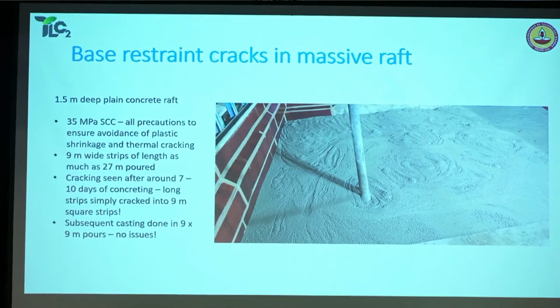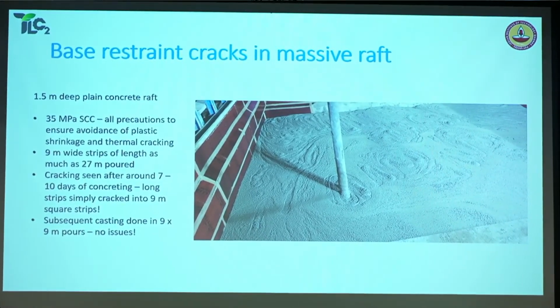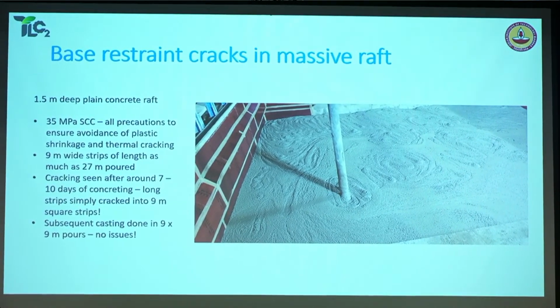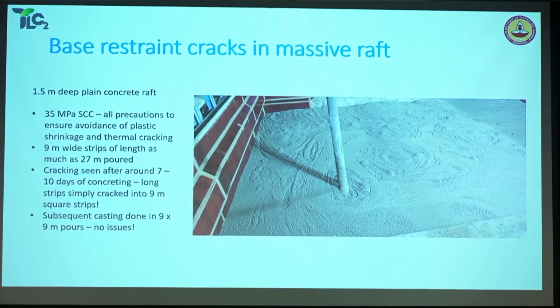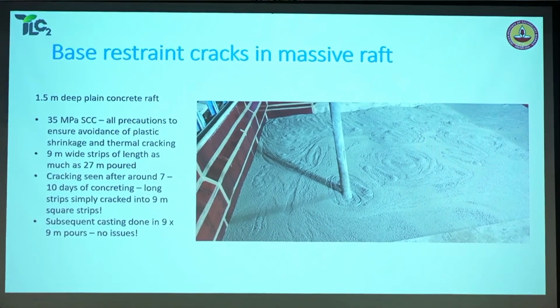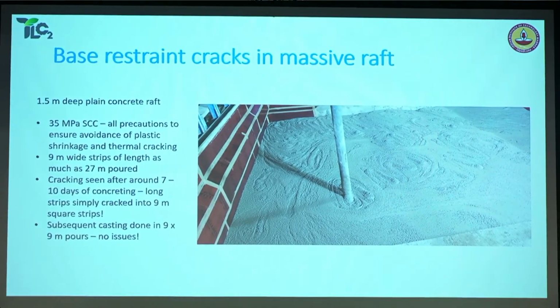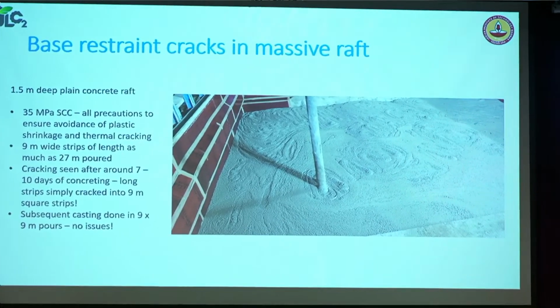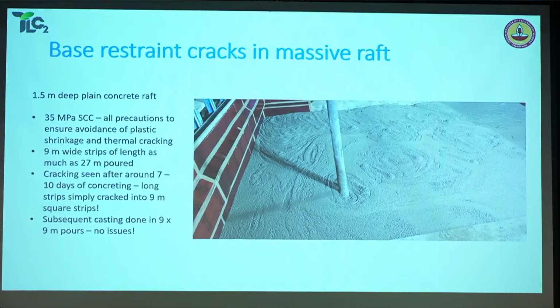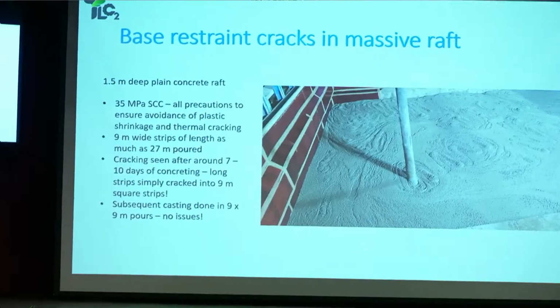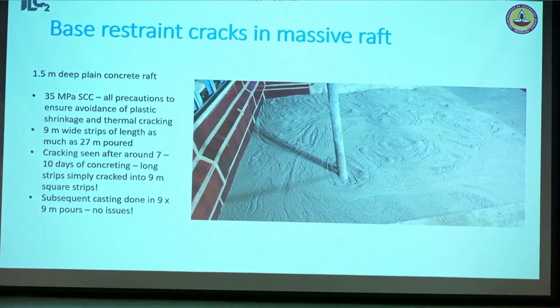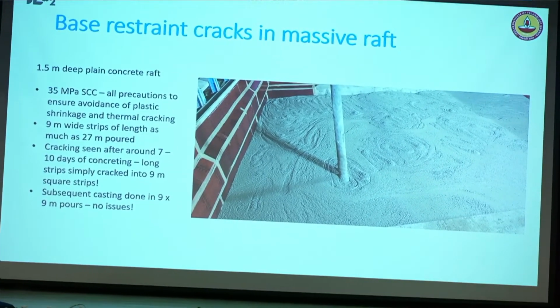Now, that doesn't mean that it failed. It just showed that that should have been the size of the slab that you first did. And actually, if you follow some well-designed, defined design procedures, you'll know that this is actually true for the kind of depth of the slab. More than 9 meters placement is likely to result in very high levels of stress. So subsequent casting was done 9 by 9 meters. There was absolutely no issues in this project.